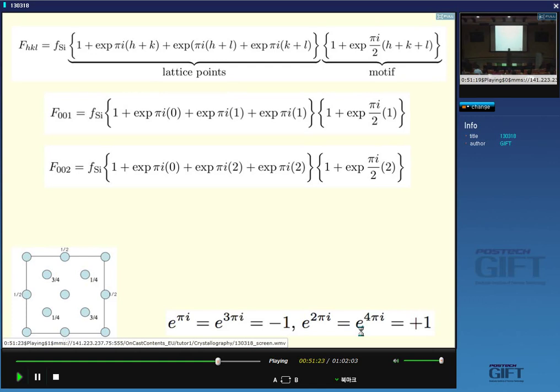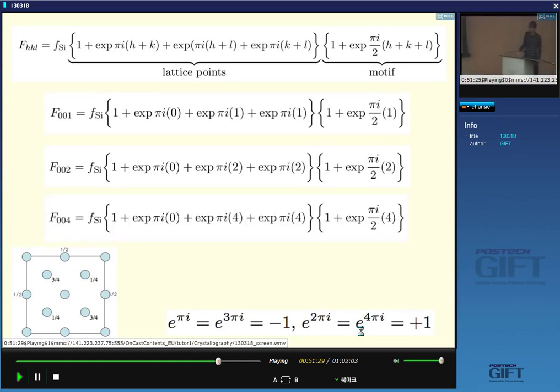Let's see for 004. So this time, this will be even. Okay? And therefore, you will pick up a 004 reflection, which is for this set of planes. So you can distinguish a diamond structure from a copper structure because you do not get a 200 or a 100 reflection. Everyone happy with that? Now I'm using simple planes here only to illustrate by looking at this diagram, but you can substitute any plane into that equation that you like to calculate the structure intensity. Actually, these are amplitudes.